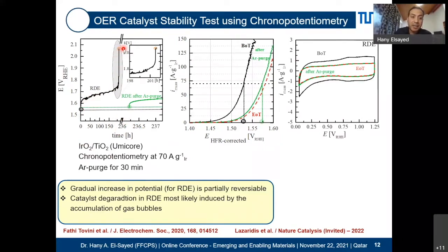And of course, at the end here, you say, well, now potential jump means I have no catalyst. But the interesting part is, again, you purge with argon, and all of a sudden, you start again applying the same constant current. You potentially start right here. So the potential just didn't go up because you lost the catalyst, but because you just shielded. You prevented the catalyst from seeing the electrolyte, and it starts normally from here, and so on.